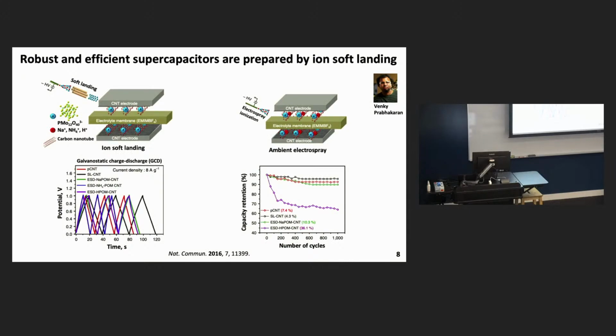So what we did here is we prepared a supercapacitor device through this ion soft landing approach, and we did it two ways to try and understand the benefits of mass-selected ion deposition. On the left-hand side here, you can see these clusters are deposited. They come down basically as discrete ions without any solvent and without any counterions. On the right-hand side, we did a deposition without mass selection just on the benchtop. And here you have counterions and solvent present.